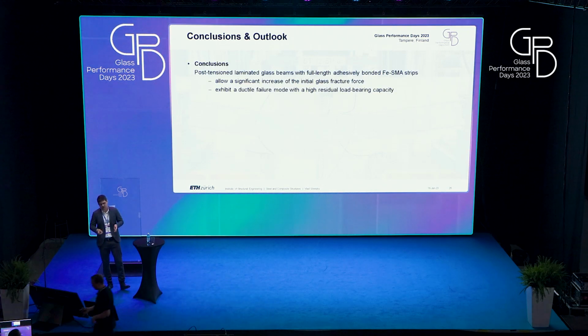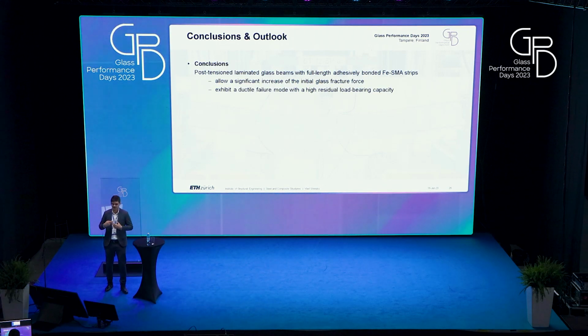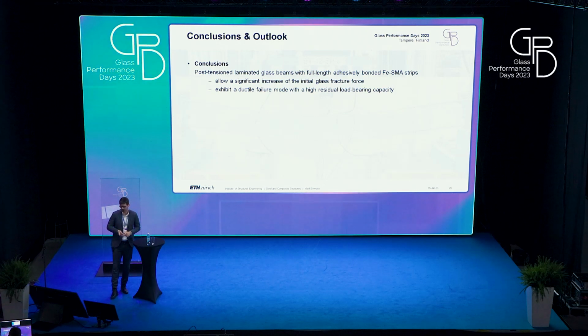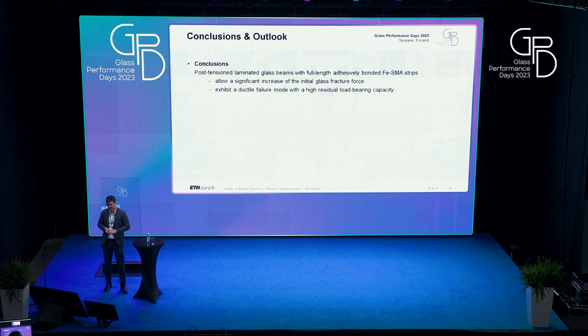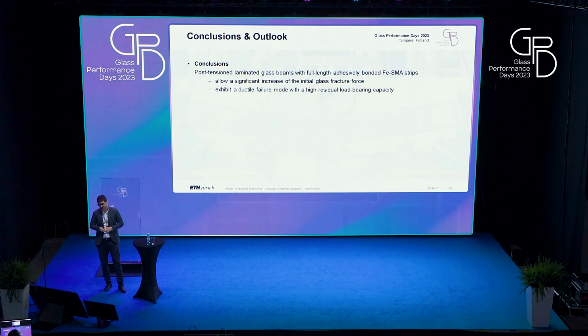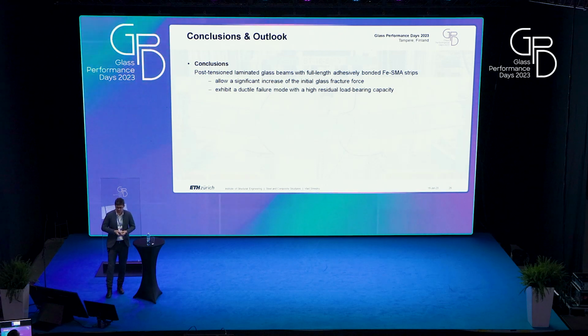Based on the experiments that we performed, we showed that post-tensioning laminated glass beams with full-length adhesively bonded strips allow a significant increase of the initial glass fracture force, and it's also possible with these systems to reach a ductile failure mode.